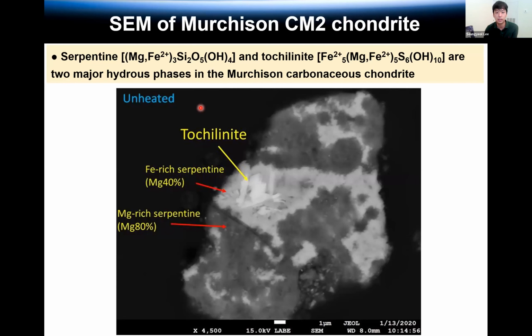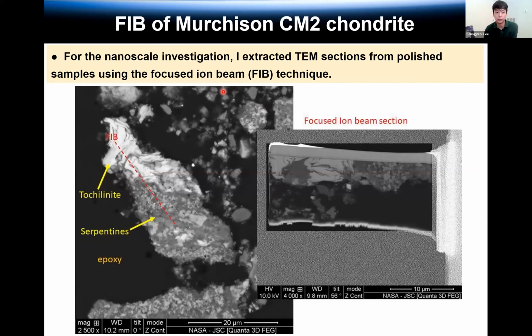Murchison chondrite, a BSE image. Serpentine and tochilinite are the two major phases in the Murchison chondrite. This is a tochilinite phase, this is iron-rich serpentine, and this is a magnesium-rich serpentine phase. This scale bar is 1 micrometer. But the problem is that serpentine and tochilinite are nanoscale clay minerals and nano minerals, so SEM has a limitation in seeing those phases. So we need nanoscale investigation. By using the focused ion beam technique, I extracted the interesting area for TEM analysis. I extracted this area and made the focused ion beam sections.